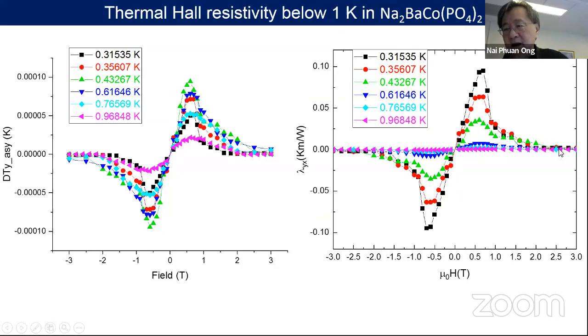It dies. And above about 2 Tesla, we cannot resolve any thermal Hall resistivity because that is the signal and we cannot see it. So when you invert this matrix to get the thermal conductivity, you get basically large fluctuations here that are not physical, that are not reliable, right? You need to increase the reliability of the measurements by maybe a factor of 50 to get any information on the thermal Hall conductivity at high fields, right?